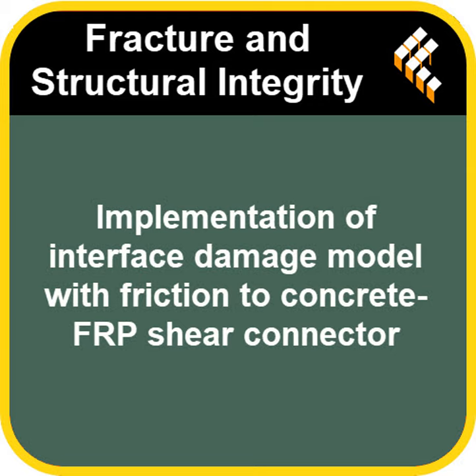It really is. These connectors are made by cutting regular shapes like notches or grooves into the vertical part of the web of the FRP beam. Then, when you pour the concrete deck around it, the concrete flows into these recesses. What you end up with are these vertically embedded FRP dowels and interstitial concrete dowels. Essentially, the concrete and the FRP physically lock together like jigsaw pieces. It creates a really strong interlocked connection for transferring those forces. Okay, so the aim is to stop any slipping or separation.